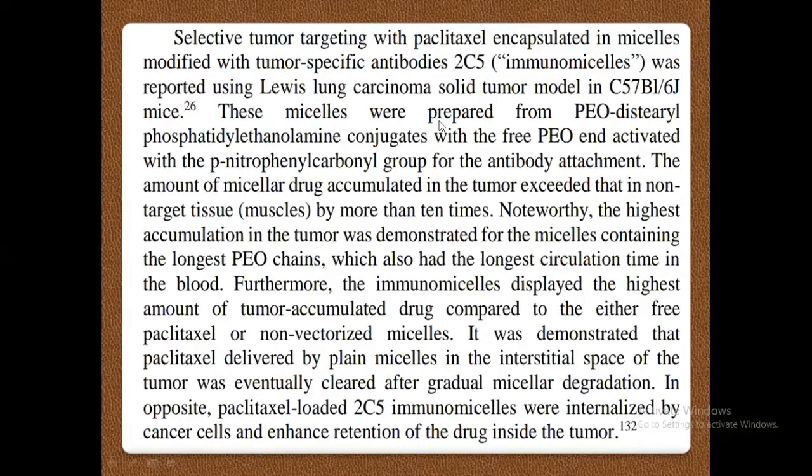These micelles were prepared from polyethylene oxide-distearoyl phosphatidyl ethanolamine conjugates, with the free polyethylene oxide end activated with the para-nitrophenyl carbonyl group for the antibody attachment. So the antibody is attached to these micelles on this para-nitrophenyl carbonyl group.